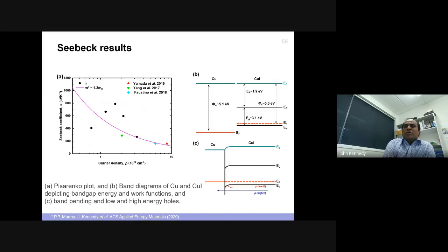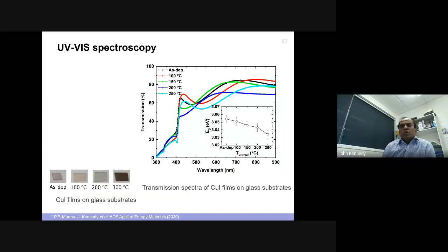So the curve is the effective mass concentration. As you remember, that's m*, which is directly proportional to the Seebeck coefficient. So that's something we have been trying to fit with the theory and explain why we got the high Seebeck coefficient. As I said, transmission is good. You can actually go up to 80%, in some cases even 70, 90%. And we did a thorough study.